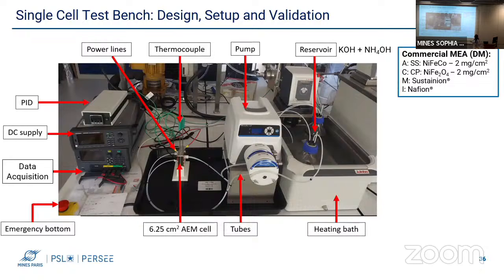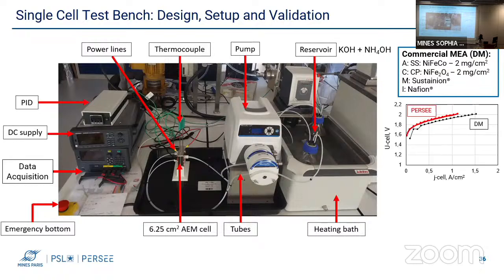The test bench also consists of the reservoir, which contains the feed and the electrolyte solution, placed in a heating bath. The peristaltic pump allows the circulation of the feed into and out of the cell. PID controllers are used to control the temperature of the electrodes. The DC power supply provides the electrical current, and the data acquisition system is used for data storage. The obtained polarization curves were similar to those provided by the manufacturer, which allowed us to say that the performance of this test bench was validated.